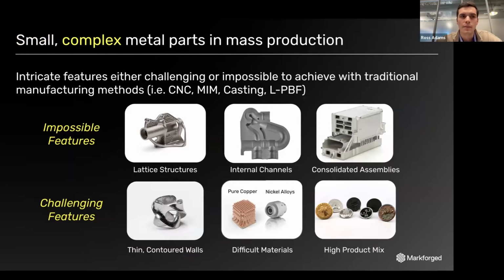Now let's talk about complexity. The more complex, the better. Now, intricate features are either challenging or outright impossible to achieve with traditional manufacturing methods. We often see parts made through CNC machining, metal injection molding, investment casting, and laser powder bed fusion being the incumbent metal 3D printing process. We like the impossible features, things that no one else can do in any other way. And the type of aspects that we see here are lattice structures, being able to lightweight the component, being able to put filtration designs into the component, and doing that conformal within it. A lot of great opportunities for lattice structures, and we can go down to about 200 micron bead thickness on these struts.